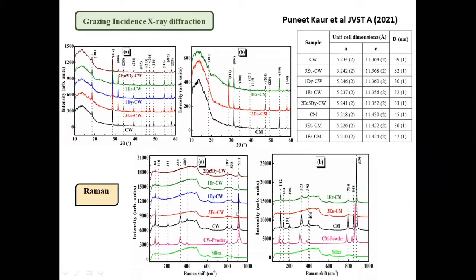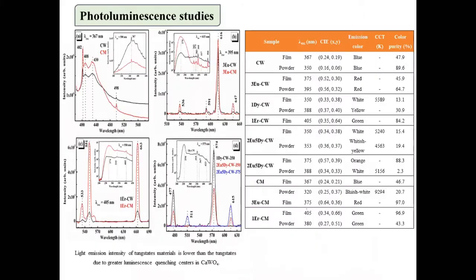And these are the Raman patterns. Raman patterns are very similar to those of the powder samples. So the same phase is formed by PLD deposition. So that is the advantage of pulsed laser deposition. It gives you a very good stoichiometry, which you cannot get by sputtering or by electron beam deposition techniques.